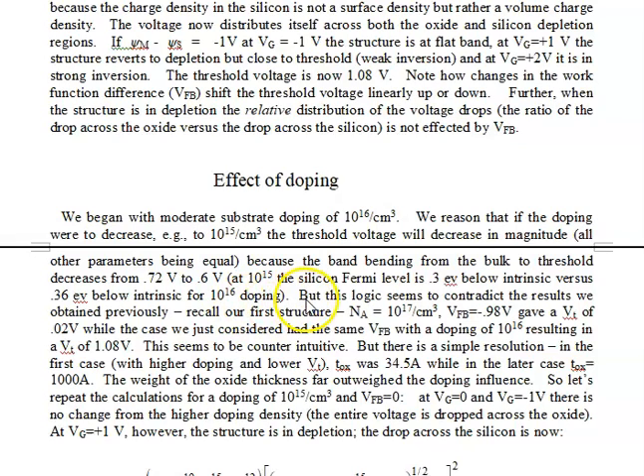But before we go there, this is logical, it's intuitive, but this logic seems to contradict the results that we have already obtained. In our first case, going back quite a number of pages, maybe 6 or 7 pages, we had 10 to the 17th, we had the flat band voltage of about -1 volt, and we had a threshold voltage which was extremely low, plus 0.02 volts. While the case we just considered here, same conditions, except for the lower doping, we had a threshold voltage which is higher, exactly the wrong way.